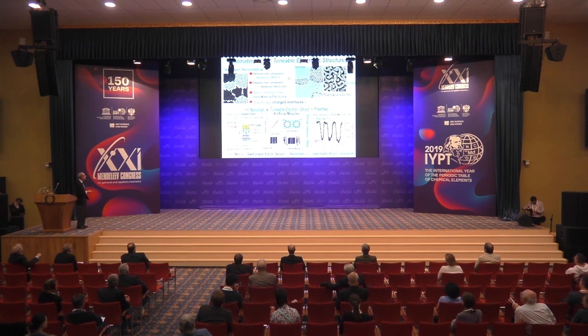Another application is artificial muscles. By using the charge density-induced variation in length of carbon nanotubes, we can build artificial muscles. What we do is we have the muscles sitting in an electrolyte, and when we apply a charge, these carbon nanotube threads twist, and when we discharge them, they untwist. You can see here the twisted state and the untwisted state. And by twisting and untwisting, the length of the carbon nanotube changes.